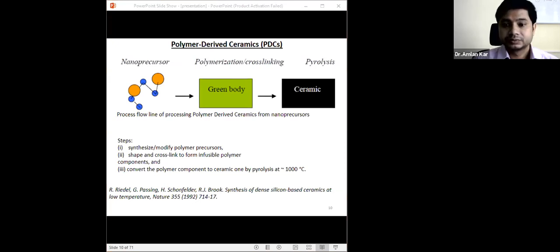Okay, let me discuss. So PDC processing includes, here I have included, the three basic steps. The first is the synthesization or modification of the polymer precursor. The second step is to shape and cross-link to form an infusible polymer component, and the third step is to convert the polymer component to ceramic by heat treatment at a particular temperature. Okay, so in the present case we have heat treated at 1000 degrees centigrade.